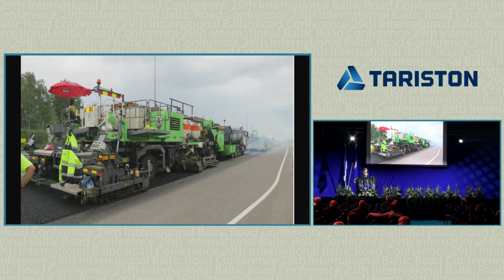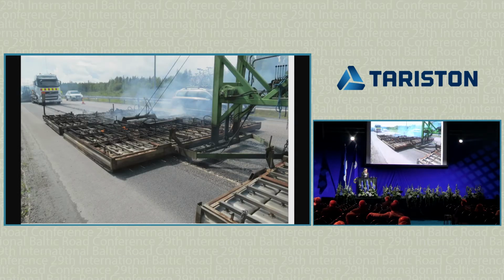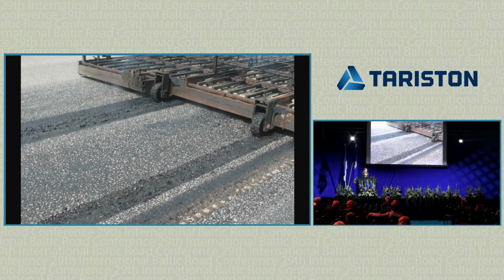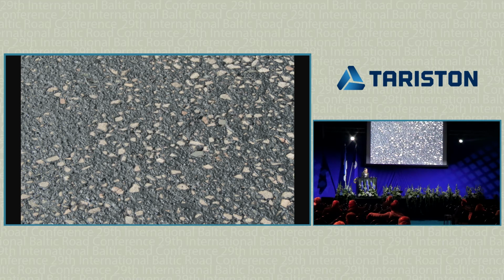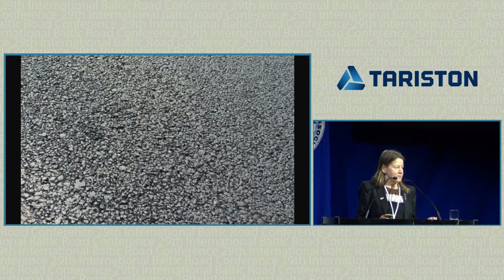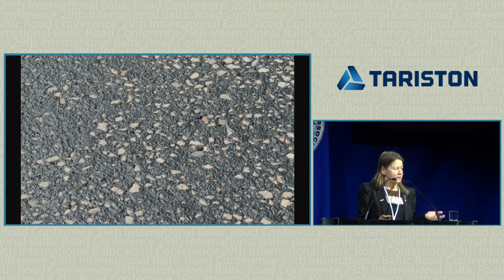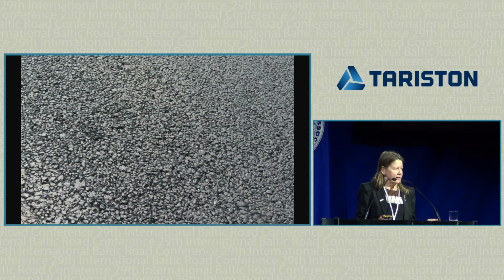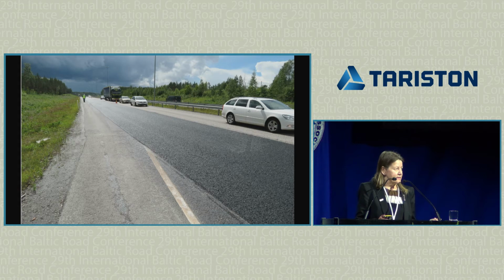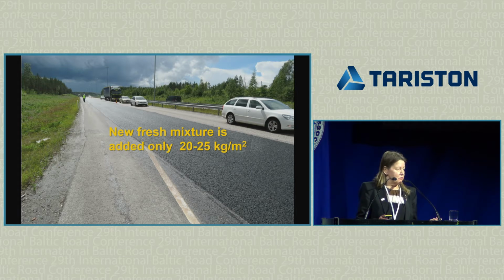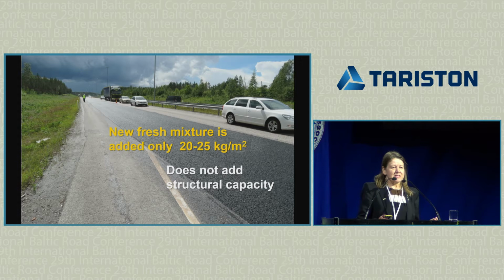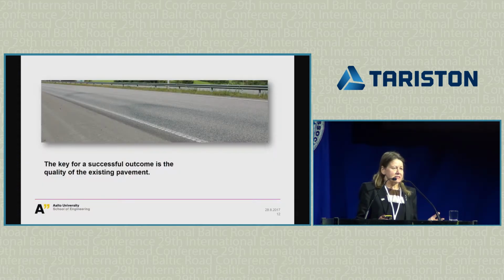So a few pictures. Here is the convoy, heating elements. This is the heated surface. This is how it looks. Ready surface. Now the admixture has been added, scarified. The heated surface is scarified, then admixture added, rejuvenators added, then it's laid and compacted, and we have a nice ready surface for driving. So as we add only these 20-25 kilograms, it makes it a cheap way to fix the roads for running. But it doesn't add any structural capacity, so that's the key thing to remember, that if we need structural capacity, we need to use something else.